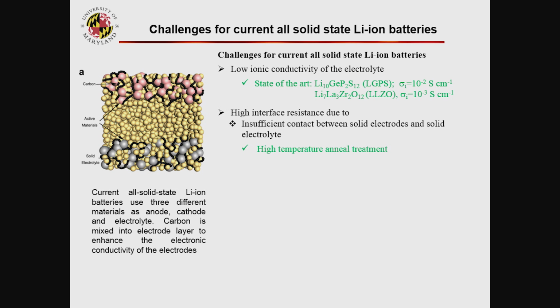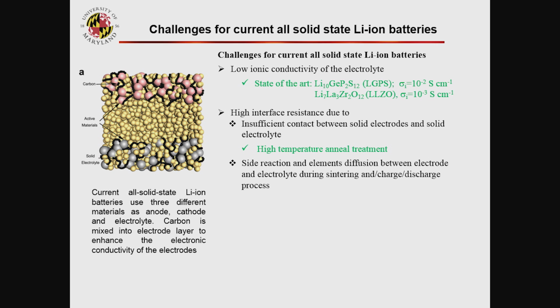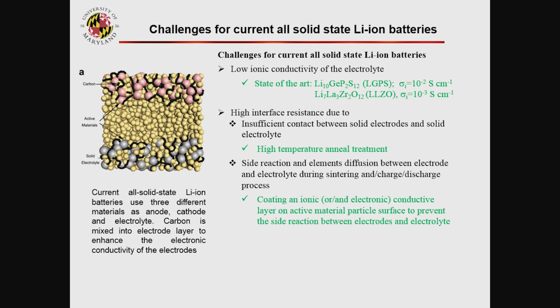Second, the technology right now is that we try sintering, to make the interface contact as large as possible. The second challenge is that the electrode and electrolytes react during the sintering or during charge-discharge. When lithium moves out and crosses the electrolyte-electrode interface, it carries some ions that also move. So one is a chemical reaction, one is an electrochemical reaction. Normally what we do is coat an ionic or electronic conducting material to separate electrode and electrolytes.